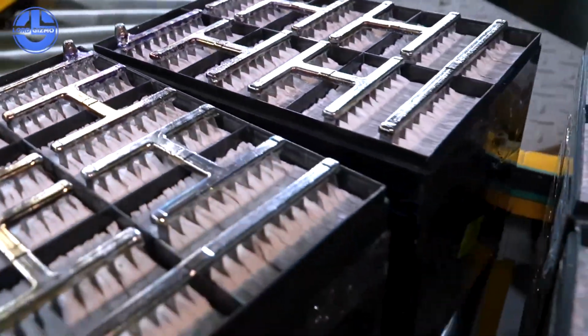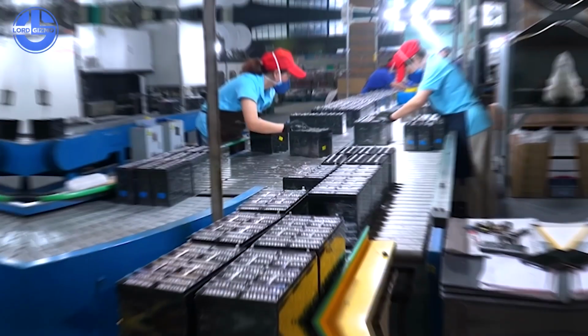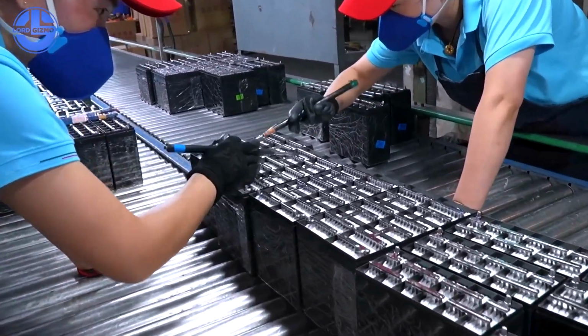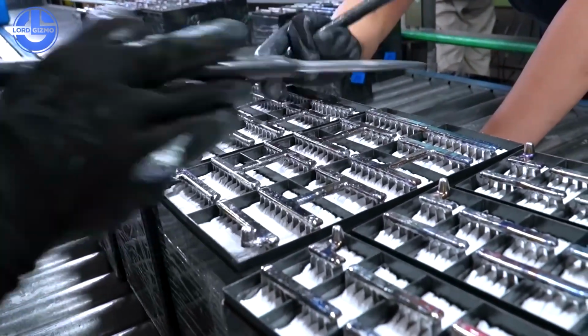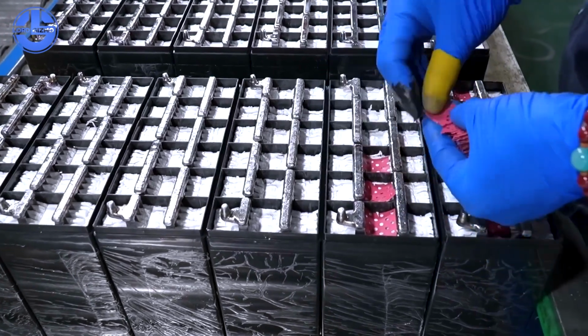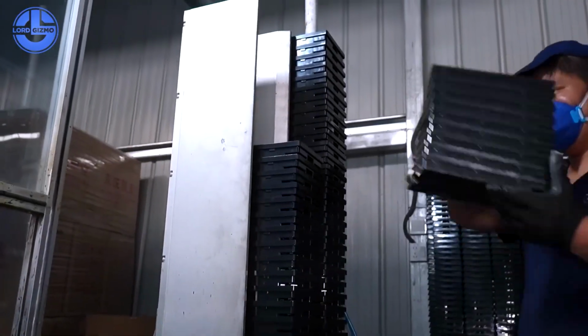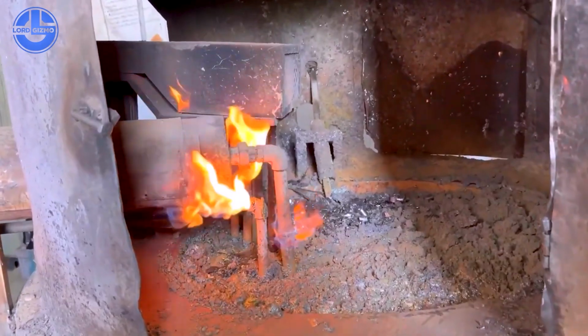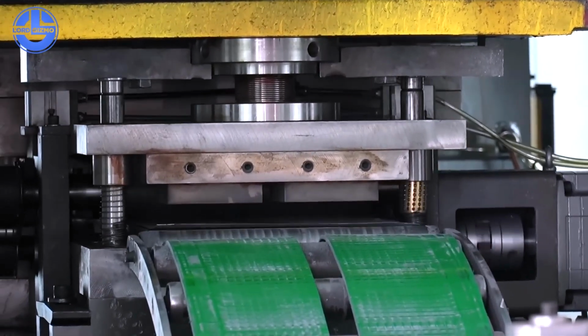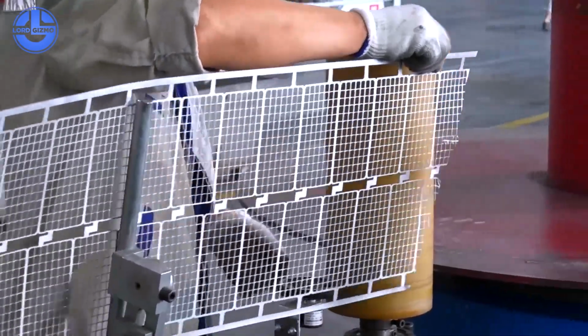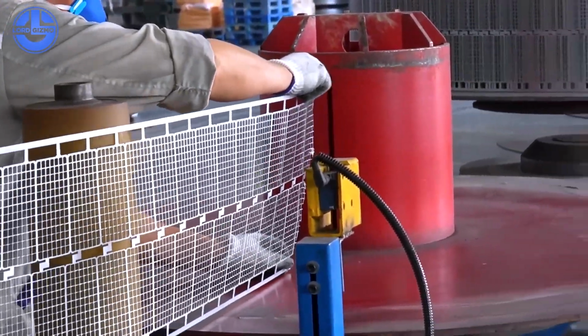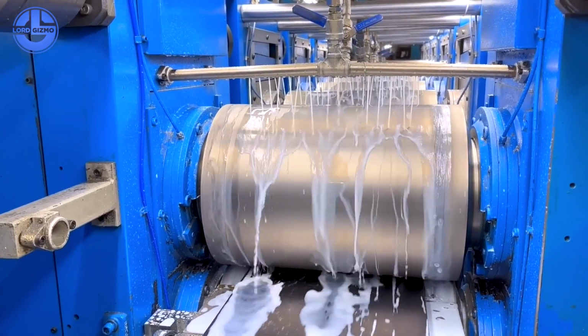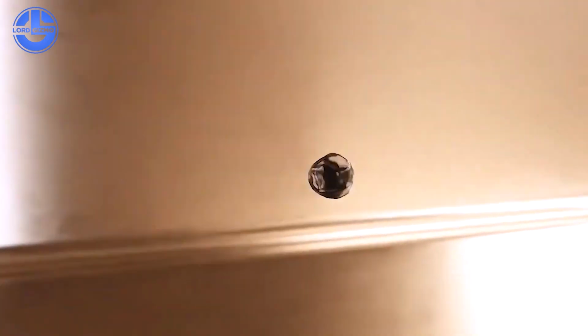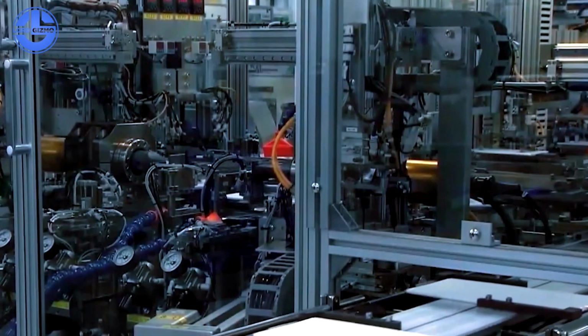This is where battery manufacturing becomes part chemistry lab, part high-tech kitchen. Massive mixing systems combine the active materials with binders, conductive additives, and solvents in proportions measured with pharmaceutical precision. But unlike cooking, this mixing happens under conditions that would make a laboratory jealous. The mixing chambers are sealed environments where humidity is controlled to fractions of a percent. Temperature stays constant within half a degree. The mixing itself involves forces and speeds that would turn ordinary materials into dust, yet somehow create perfectly uniform dispersions of microscopic particles. For cathode materials, the process involves solvents so toxic they require special handling procedures. N-methylpyrrolidone, the primary solvent, is so dangerous that exposure limits are measured in parts per million. Yet it's essential for creating slurries that coat perfectly and maintain their properties throughout the manufacturing process.